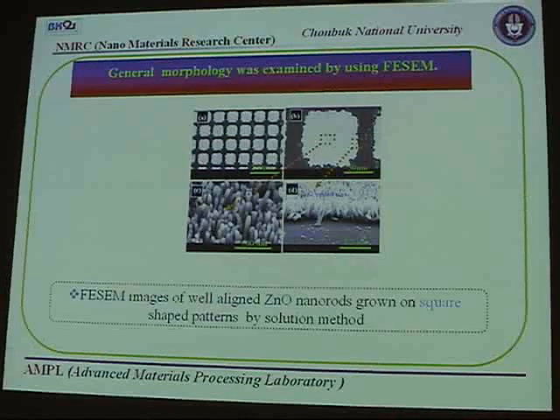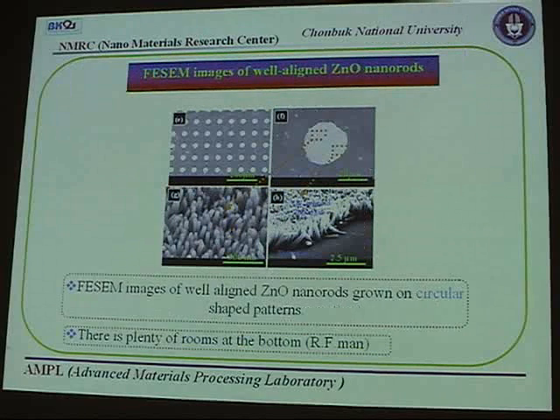This figure presents the general morphology, FESEM images, of selectively grown zinc oxide nanorods on a patterned substrate. Each nanorod has a diameter of about 50 to 60 nanometers and a length from 600 to 700 nanometers. In the next figure, we chose two types of patterns by using a very simple polymer mask. As a masking material, it is a soft mask, and it is very cheap compared to a metal chrome mask for patterning the substrate. So we use two types of pattern, circular and square shape, to obtain the zinc oxide nanorods at selective positions.